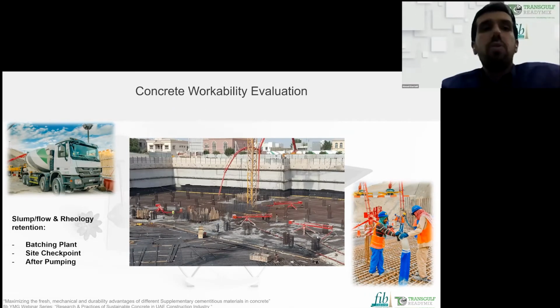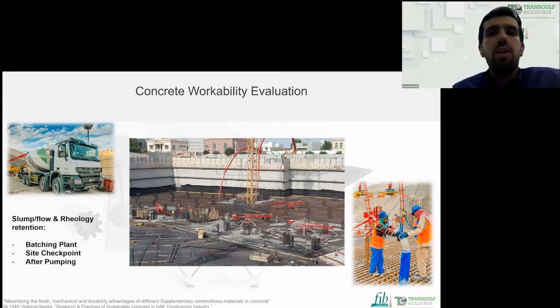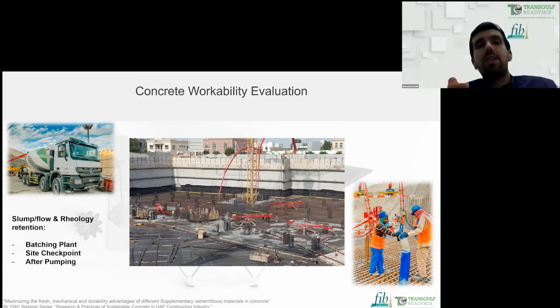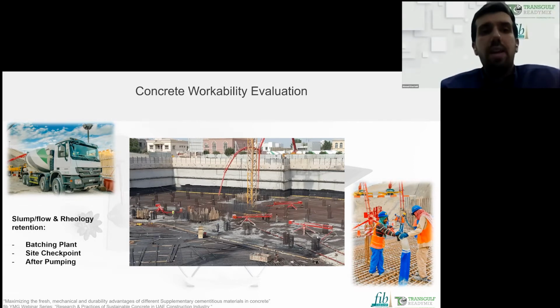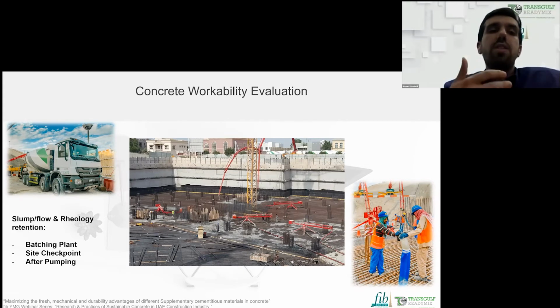Starting with the fresh properties, or concrete workability. Concrete workability is assessed in the industry at two points, at the batching plant or at the site, while it is being ignored or missed, I can say, after pumping, specifically when the pump is being used. And we know that most building structures use the pump as normal. Once the concrete arrives at the site, it is checked for acceptance to be cast or not. Usually the check is a slump test, while the slump test is actually not a check of workability, it's mainly a check of consistency. Of course, it gives an indication of the workability, but the true assessment of workability will be highlighted in my coming slide. And I highlighted pumping because after pumping, the concrete can be affected by the pressure being applied to it.